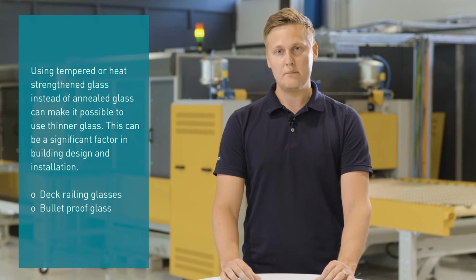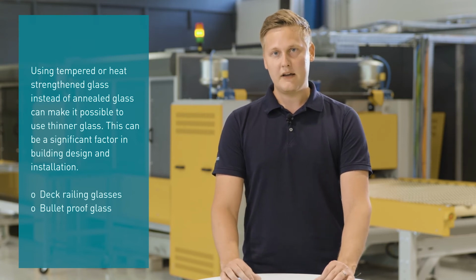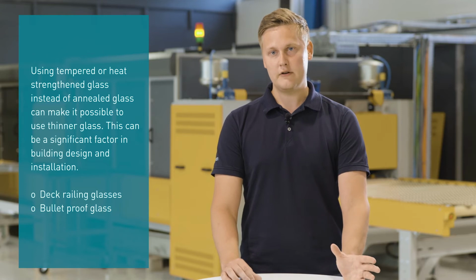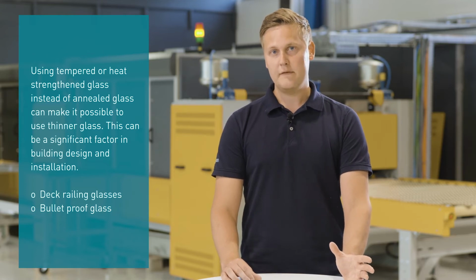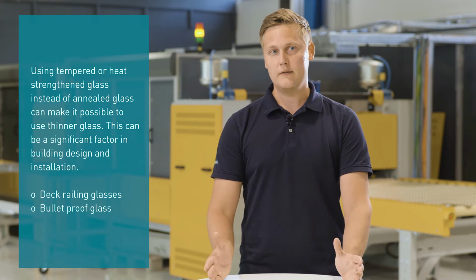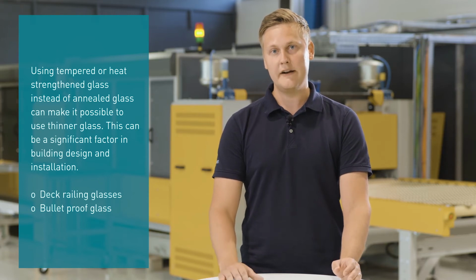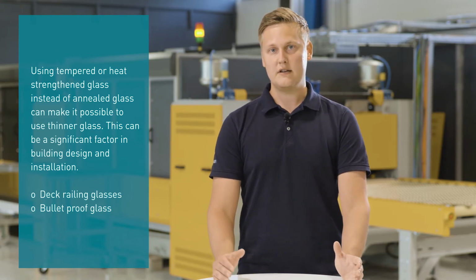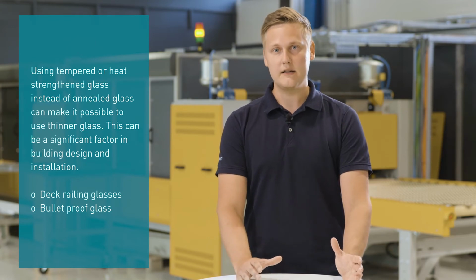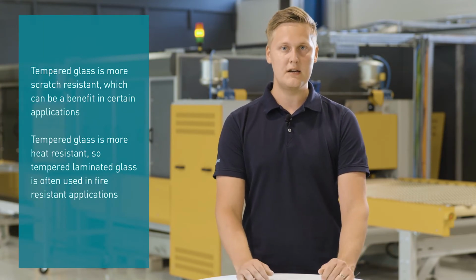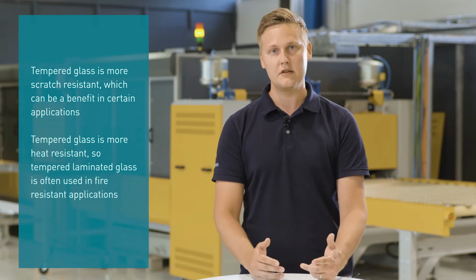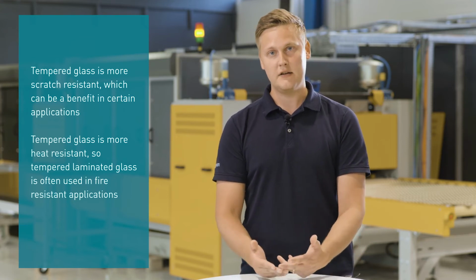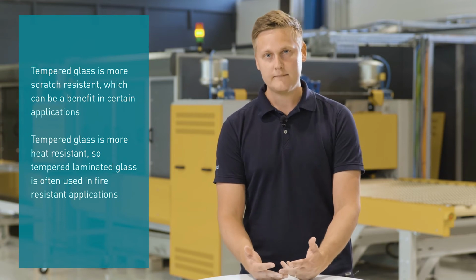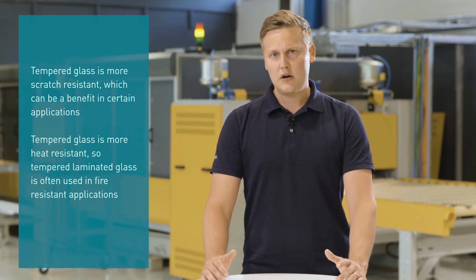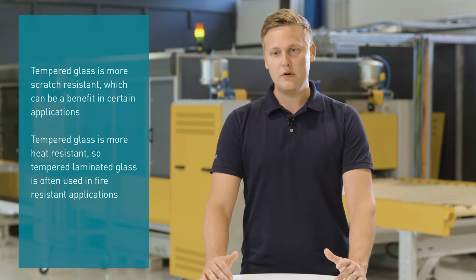Then maybe some more normal examples you see, for example, in balustrade glazing and applications where it's useful to have either the added strength or the benefit that you're able to utilize a thinner glass instead of a thick annealed glass, so that you're able to basically reduce the weight of the laminate. And this brings you multiple benefits. So for example, transportation cost, installation is easier, attaching the glass in the building is easier, etc. And I would say that these two are maybe the main points that you get.